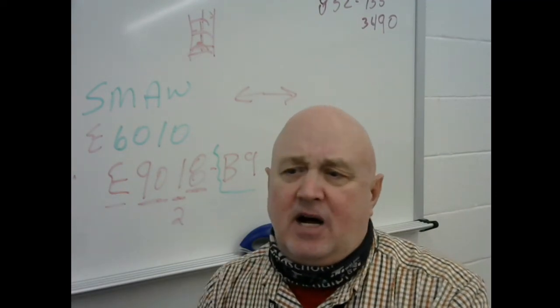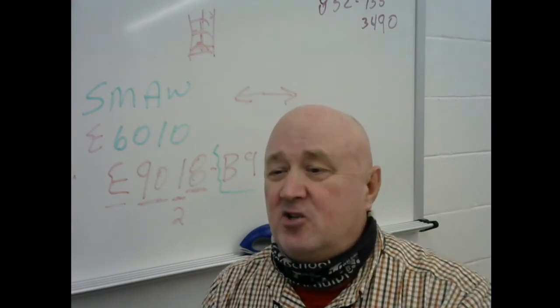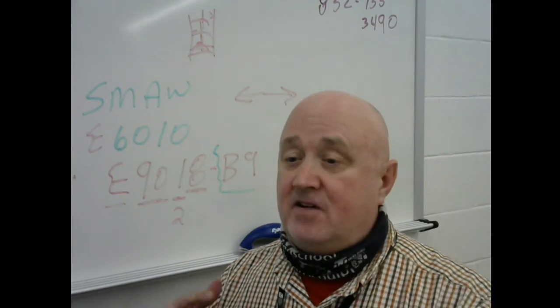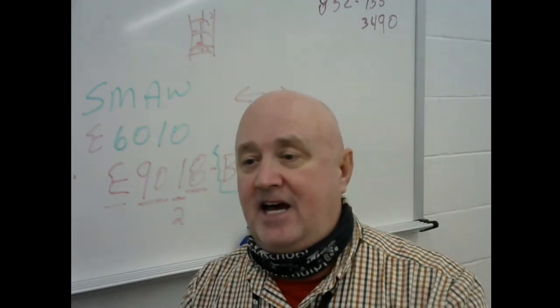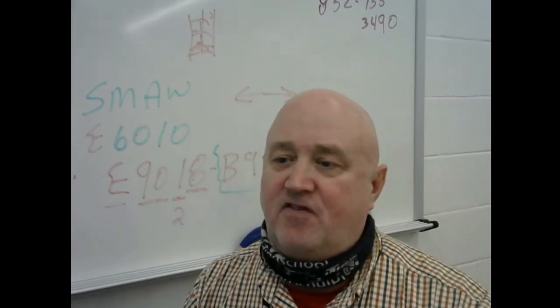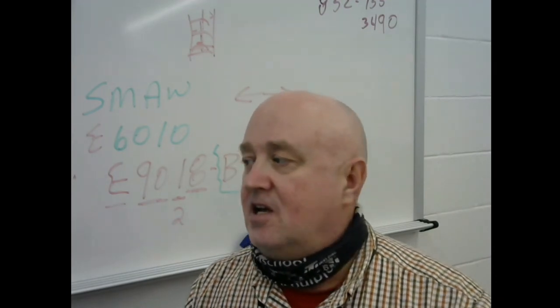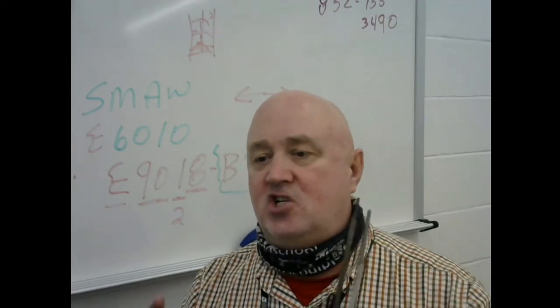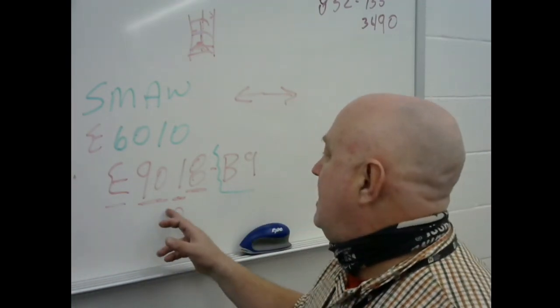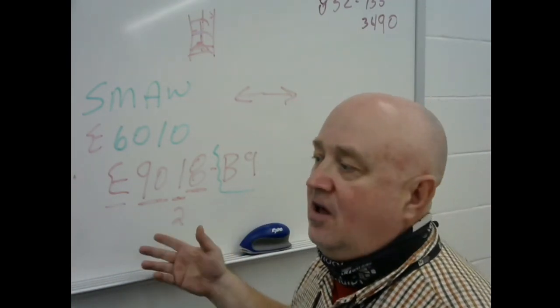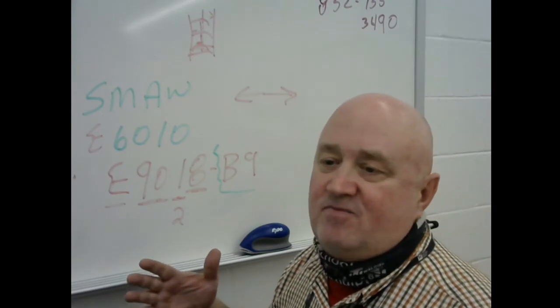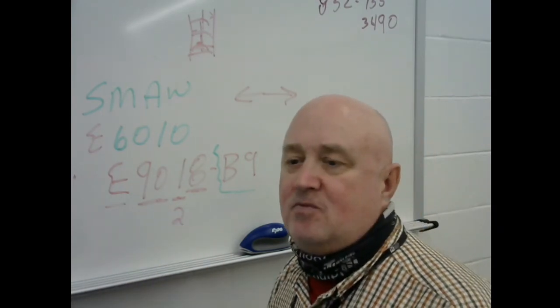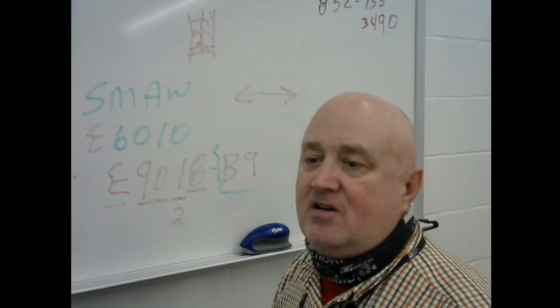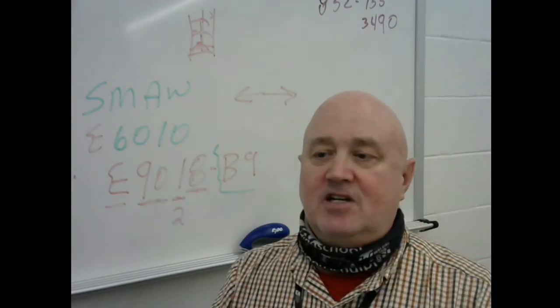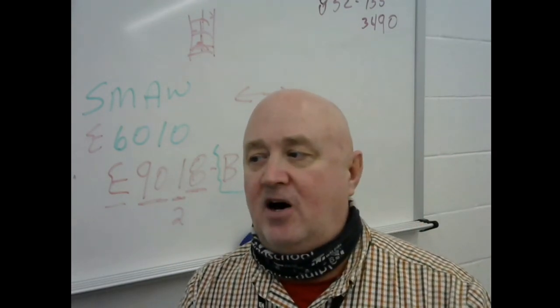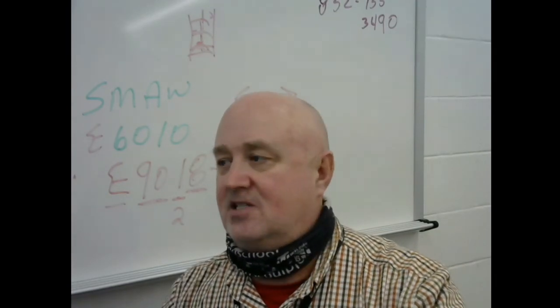So that's what we're talking about when we're talking about the characteristics and the groupings of shielded metal arc welding electrodes, when we talk about fast freeze, fast fill, fill freeze, and low hydrogen. It's just the general groupings. So 9018 would be a low hydrogen, and it would be a fill freeze. We're still going to be able to get some deposition with it, but not as much as if we use something like 7024. So that's what we're talking about when we're talking about characteristics.